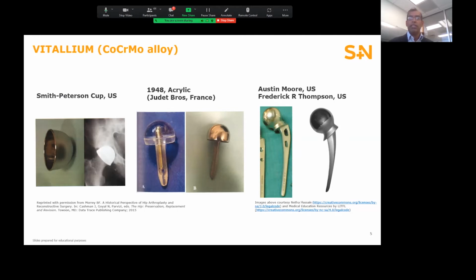During this time, other materials were still being investigated as well. For example, in the second set of images, you can see an acrylic device that was tried briefly before being abandoned in favor of cobalt chrome. By the early 1950s, Austin Moore and Frederick Thompson both separately developed Vitalium partial hip replacement components that incorporated a stem that was pressed into the medullary canal.